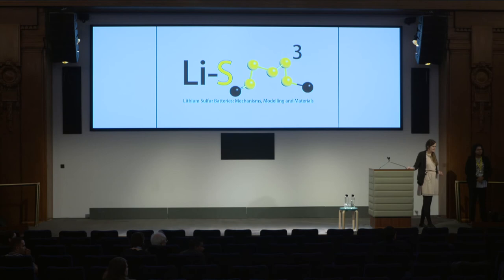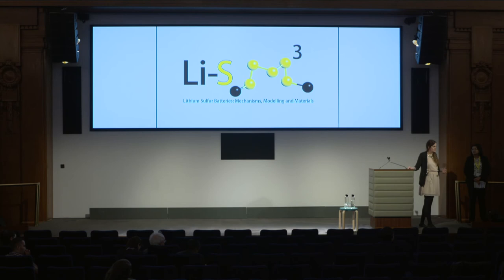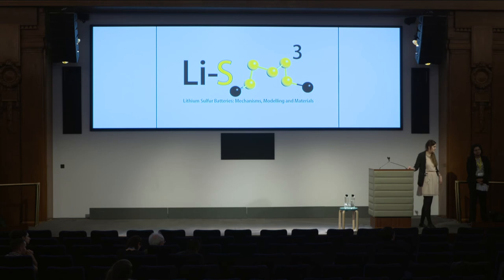Question: Is the driving force for nucleation dependent on the electrode potential? The nucleation barrier has the surface energy contribution and a part depending on solubility, so supersaturation is the driving force for nucleation. However, the macroscopic cell model includes the influence of the potential, so classical nucleation theory is coupled to standard transport equations, which carry the potential influence for the S8 species.